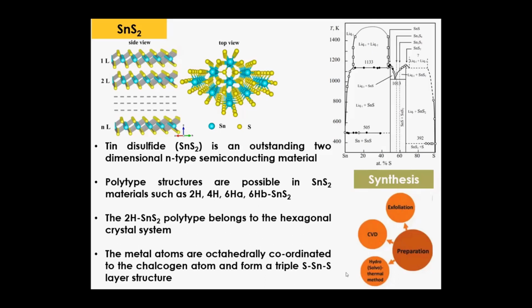CVD is very costly, and with the hydrothermal and solvothermal methods we are not able to predict the outcome, and the reproducibility is very low in this particular area. So we wanted to try a different synthesis method. If you see the phase diagram, in solid state it is very difficult to maintain tin disulfide alone. Here you have the combinations with the solid state. It is very difficult because tin will dominate in particular combinations, and sulfur will dominate in a particular combination of sulfur. So in solid state, the exfoliation is mostly based on crystals. From crystals only you can exfoliate a single layer.